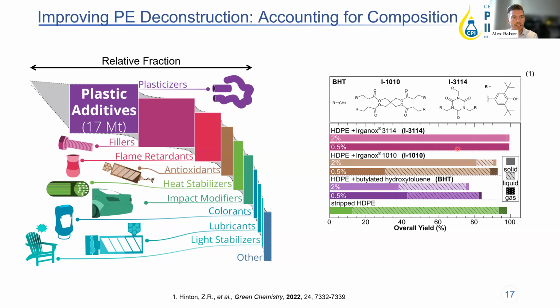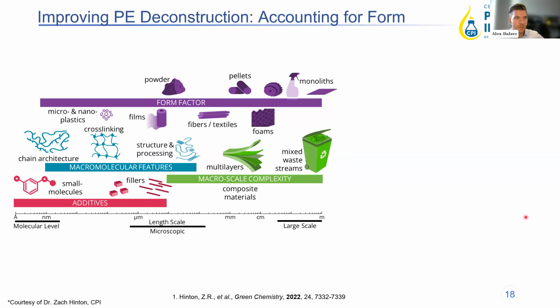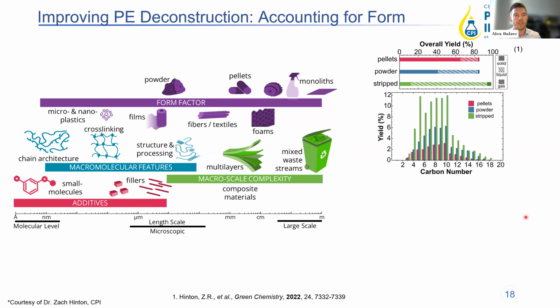And just in the case of something like this Irganox 3114, it has these nitrogen rings inside of them that deactivate the catalyst almost immediately. And so we get nearly no liquid yields and we get no reaction progress in this system. But we can also zoom out again, like I mentioned, into this form factor and understanding what size of your plastic is going to affect this process. And so we actually looked at a series of pellets that we fed in a reactor, which are on the millimeter to centimeter scale, and compare that to a powder of the same polymer that we formed that has more of a micron level scale.